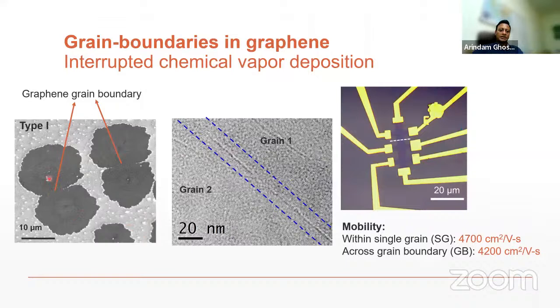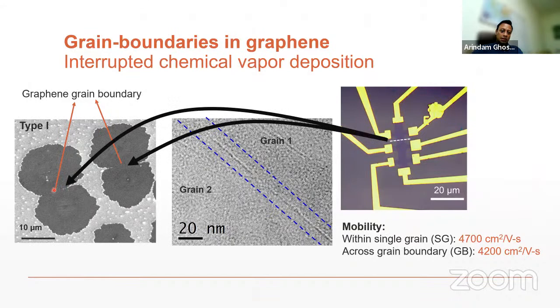Vidya and then Kimberly, and they looked at these large regions of graphene grains, which were created by what you call an interrupted chemical vapor deposition, in which we have two grains of graphene essentially coalesced in this region, and a grain boundary is formed here. And you can see the grain boundary can be extremely narrow. This is about 2 nanometers to a few nanometers in width. And this is where the challenge in actual magnetic probing can come into play. However, our ability to make devices is that we could arrest the grain boundary in an electrical device. This is essentially this grain boundary in these regions.